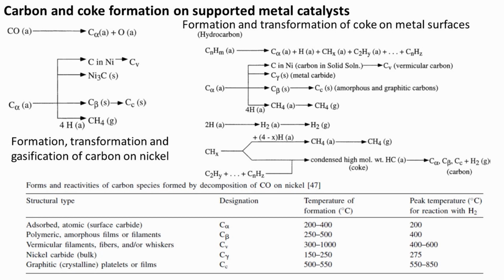The tips for preventing carbon deposition and coke formation include operating under conditions that minimize formation, like in Fischer-Tropsch synthesis. You have to operate at a sufficiently high H2 to CO ratio so that precursors to inactive carbon formation are kept at lower coverage by gasification with hydrogen.